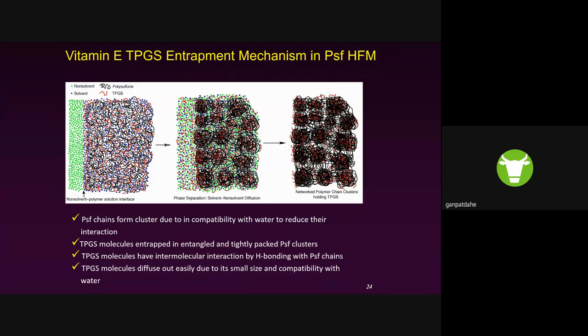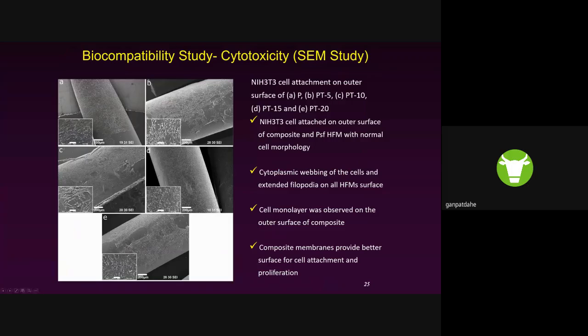So further, since this material is being developed for hemodialysis application, it's very important to evaluate this material for a biocompatibility study. So what we did, we take these hollow fibers and we sterilize those hollow fibers, then place those hollow fibers in the cell culture dishes and grow the cells on the hollow fiber.